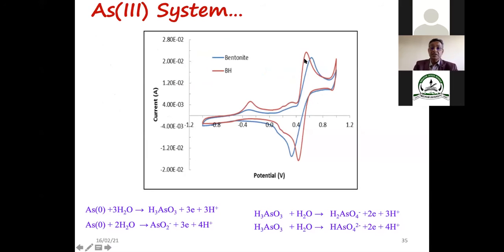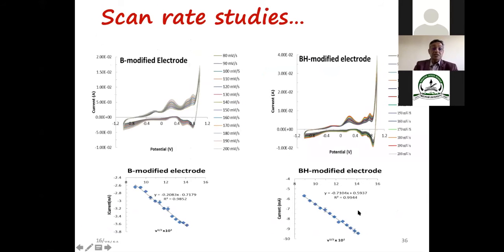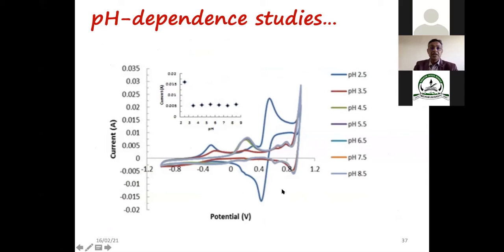How is this arsenic taking place, the oxidation and reduction? The different peaks will be coming, the 3 electron change that has been shown here. Now this is the scan rate study that we have done for the arsenic itself, and from that we try to calculate the electroactive surface area, which has not been shown here. This is the pH dependence study at different pH. We try to get the results particularly for the arsenic. We have seen that a very high signal is obtained at very low pH.